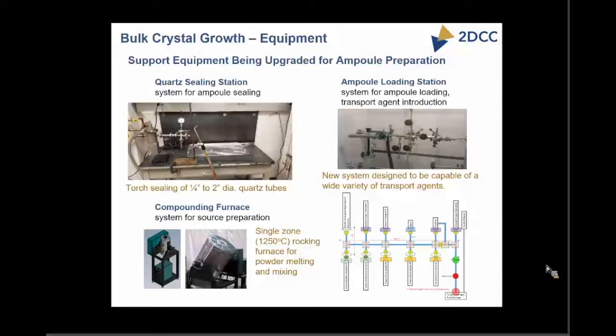Part of what I see as really an important part of the bulk growth effort here is to figure out how to really reduce the impurity levels in the crystals we're growing. And often what you need to do there is go to coated ampules, either pyrolytic graphite, high purity carbon, or boron nitride, materials that are barrier coatings on your ampule to avoid incorporation of materials from the quartz ampules themselves. And this system will be configured to allow for investigation of a variety of different types of barrier coatings on ampules.